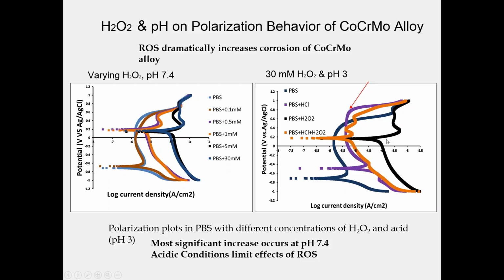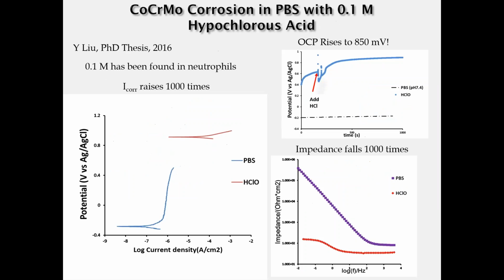Interestingly, when you go to a lower pH, so this black line on the right curve represents pH 7.4, and when we adjust the pH down to pH 3, we are suppressing the corrosion in the presence of hydrogen peroxide. So acidified hydrogen peroxide containing solutions are not as severe on cobalt chromium as pH 7.4 hydrogen peroxide solutions. So physiological pHs can induce much more significant corrosion of these alloys when ROS species are present.